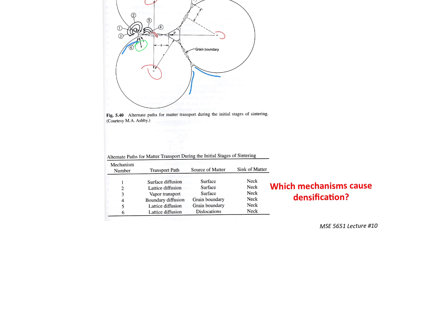And the same thing is also true for vapor transport. If it goes out into the vapor and then sits down in the neck, that's not causing those spheres to come closer together. You're eroding the surface, but you're not bringing those X's, those crosshairs, closer together. Does everyone see that? And the only ones that are, are 4, 5, and 6.